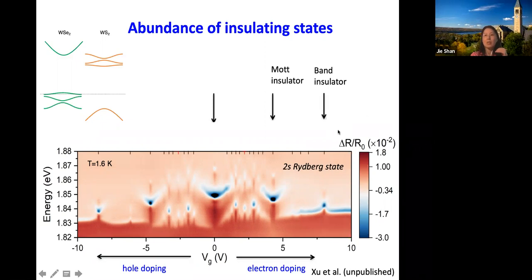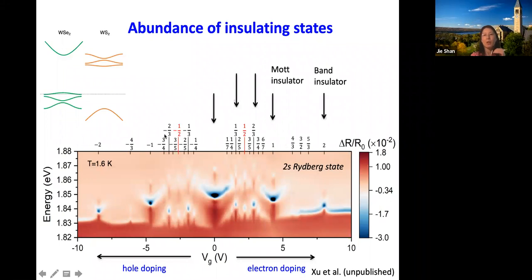We also see peaks at nu equals 1 and nu equals 2, and this is the Mott insulator, and this is the band insulator we've already talked about. And if you look at this bunch, that's 1/3 and 2/3. If you look more carefully, there are a bunch of other states, and I label all the ones that we've been able to identify.